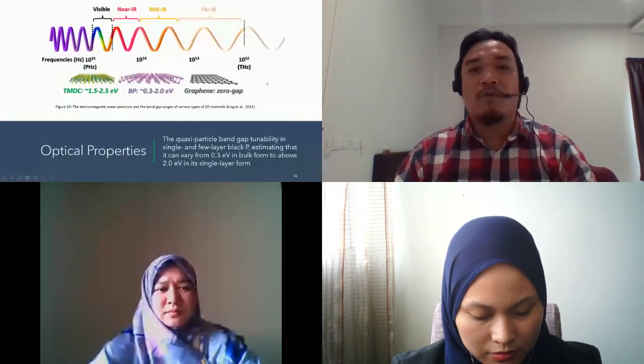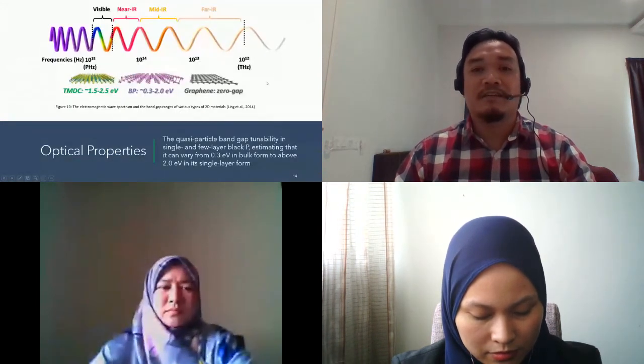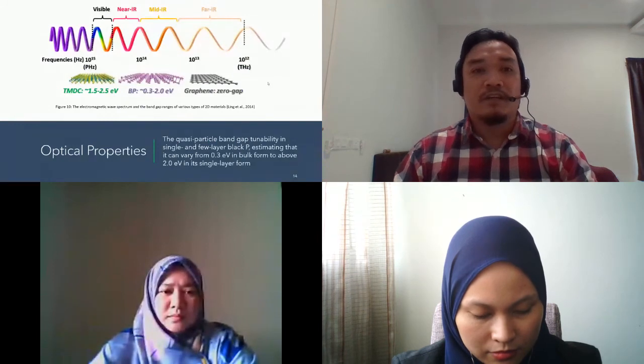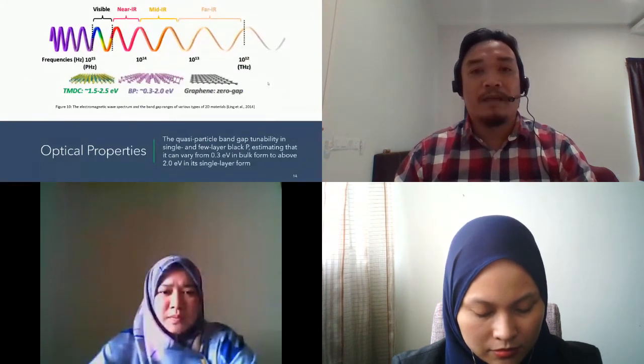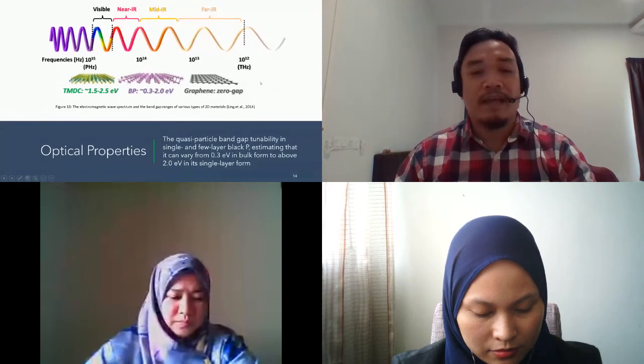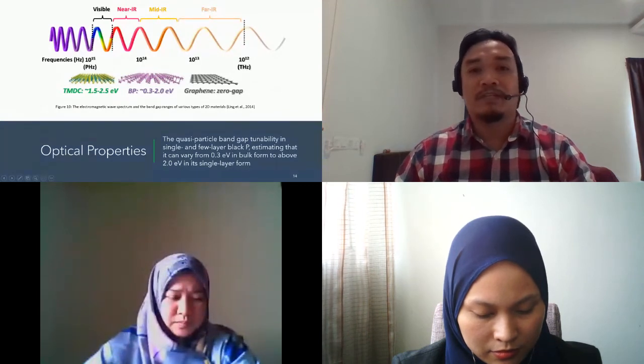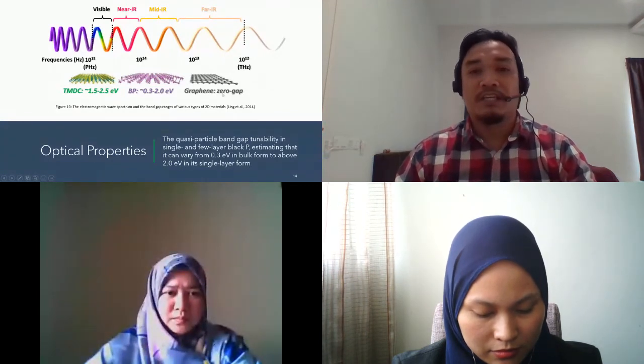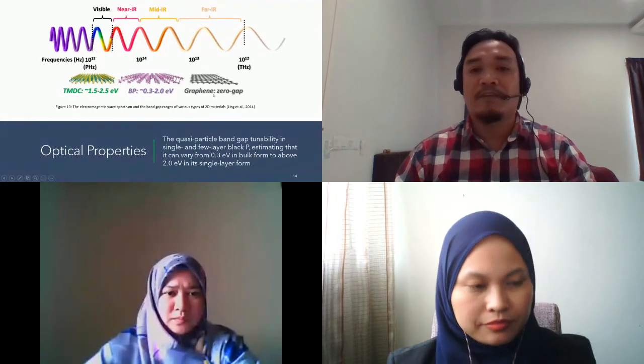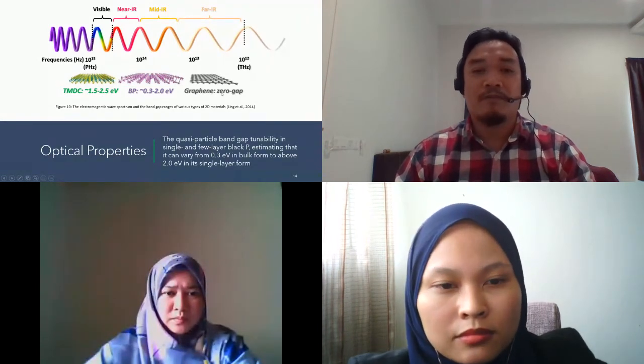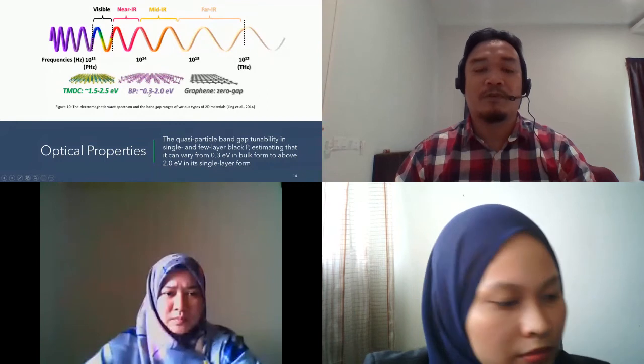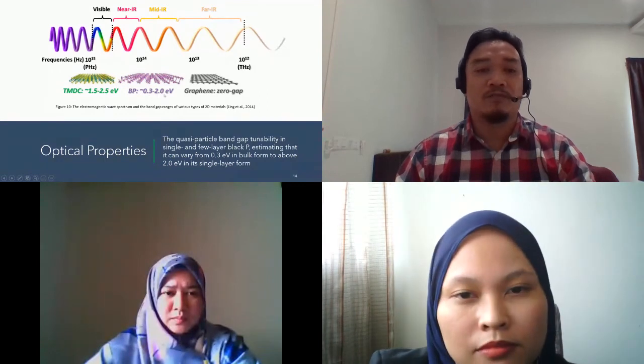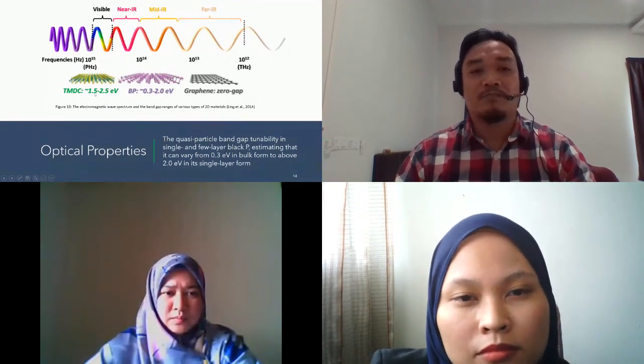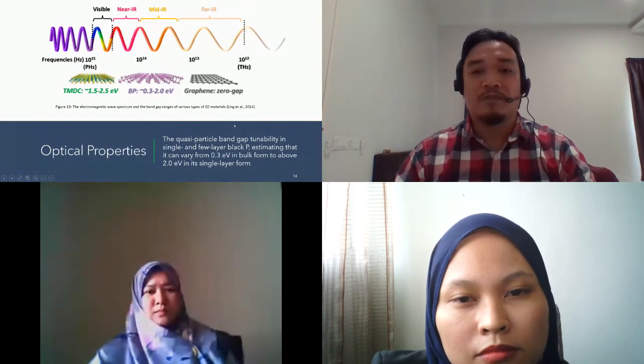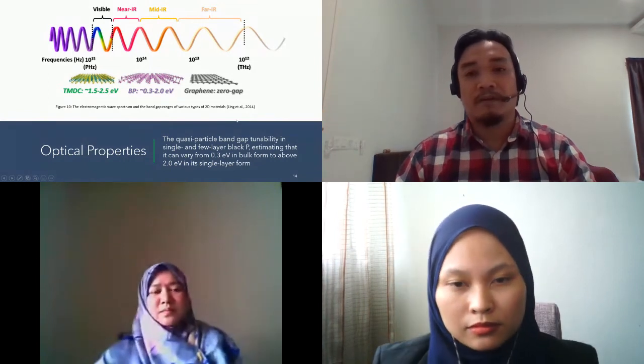Okay, and what is more interesting data is that black P has a band gap compared to graphene and TMDC. Graphene has zero band gap, but black phosphorus is around 0.3 to 2.0 electron volts. For TMDC it is 1.5 to 2.5. So it has